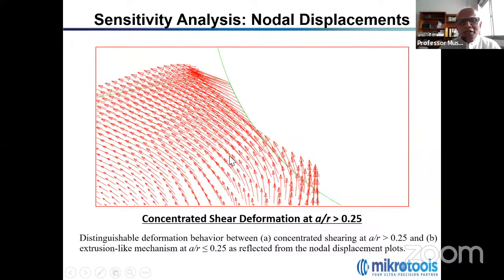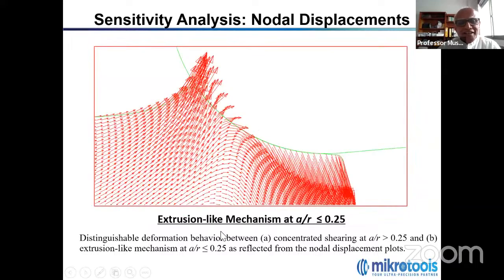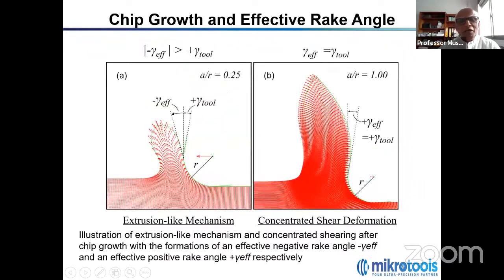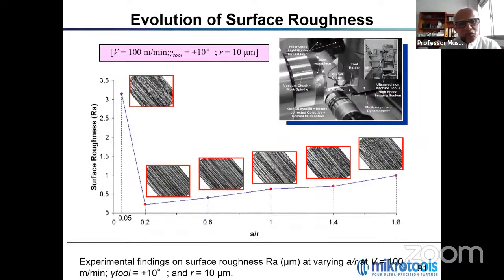Everybody, all of us, we know shearing and plowing. And in between what is happening, we try to investigate that. And we found that when A by R is less than 0.25, that reverse flow of the material takes place, which resembles extrusion. Thereby, we developed this theory of extrusion-like mechanism, where the reverse flow of the material takes place. And this is concentrated shearing, which A by R is large, and here A by R is very small, below 0.25. So first breakthrough came, and it was done in 2010.